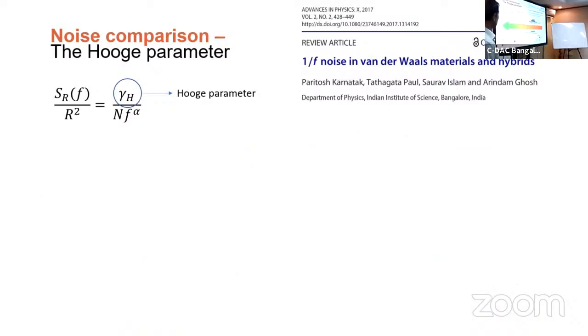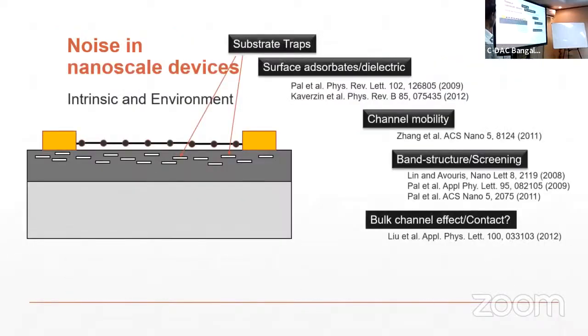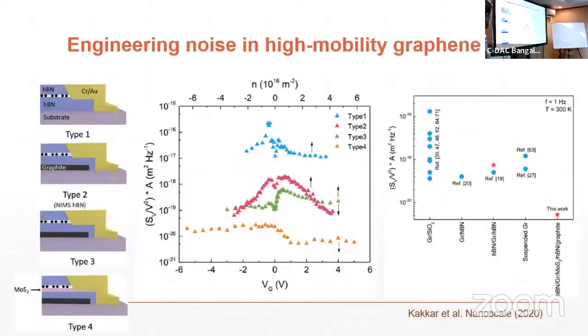Okay, so I can tell you the device that was used is this. The lowest noise that we achieved in 2D, and it's a record today in the world, is obtained by putting a layer of graphene between two layers of boron nitride and a layer of molybdenum disulfide, screening all the charges. We found silicon oxide is a bad source of charge, right?